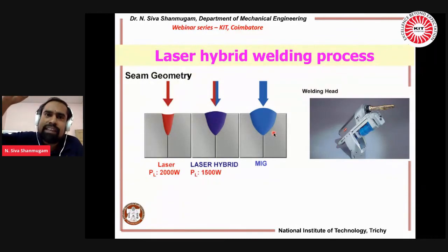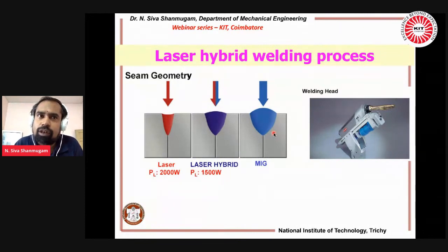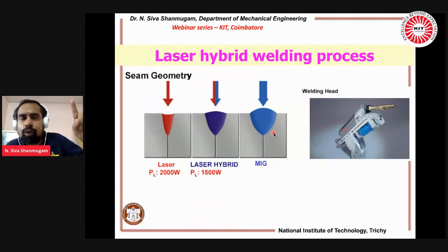We are playing with 1 mm or 0.1 mm in laser, but here the energy is focused on a 10 mm diameter. In laser you are concentrating the power on 1 mm, but in the commercial arc welding process they are concentrating on 10 mm. So it is 10 times greater. That's why when you operate with the laser, you can penetrate in depth, but the energy dissipated is very high in the commercial arc welding process.